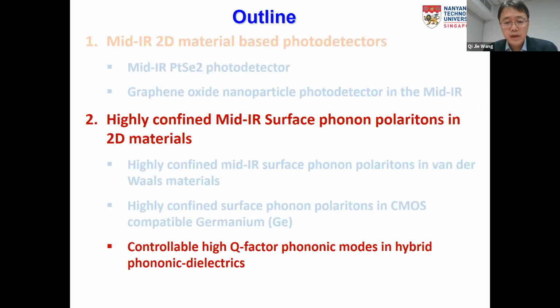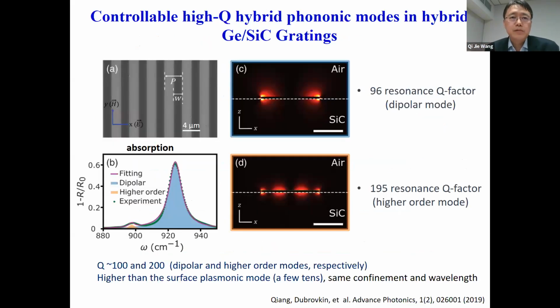And the last, I'm going to talk about how we design a grating structure in order to launch surface Phonon-Polaritons. So in the previous examples we used a tip to launch the surface Polariton mode. However, for efficient launching of a propagation mode, we can use a grating. So here we show such an example, and here the grating period is 4 micron. Of course, when we launch the infrared wave into the grating, we naturally also form a localized mode on the grating, which is, by the way, formed on the germanium on top of silicon carbide substrate. Okay, and here figures C and D show the dipolar mode and higher order mode, which show relatively high Q factors of 100 and 200 respectively.